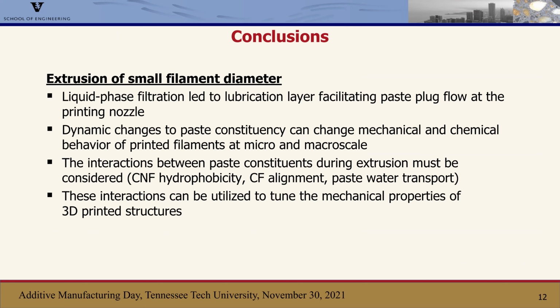So in conclusion, there are some very important things to be taken into account when you're printing with a small filament diameter, including that liquid phase filtration can change your local water availability at the extrusion point, and that these changes are dynamic and can change both the mechanical and the chemical behavior of your printed filaments at multiple scales. And then the interactions between the paste constituents during the extrusion also need to be considered, as we saw with the carbon nanofiber hydrophobicity leading to under extrusion, and with the carbon microfibers aligning with the direction of the print, as well as water being transported through our filaments during printing.